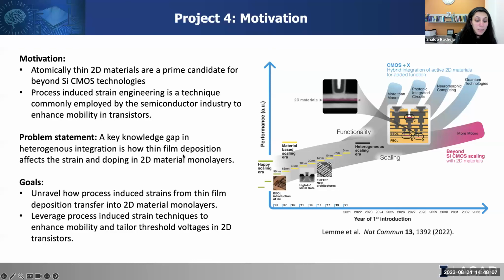So 2D materials are naturally atomically thin, and therefore they are a prime candidate for replacing silicon in CMOS technologies. And they also have some excellent properties, electronic, mechanical, as well as optical properties. But there is still a very big gap as to how the CMOS processes, such as the deposition of thin films, would affect the strain, doping, as well as the defect profiles in these 2D materials. And because of that disconnect, there's a huge amount of variance that is reported in the literature for the performance of these devices. So really the goal of this project is to develop new approaches to rationally design these 2D materials by gaining control over some of the effects that I have mentioned.